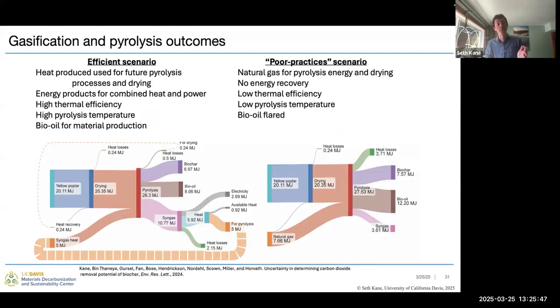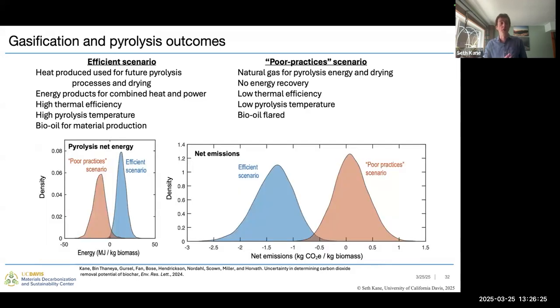In addition, it's worth thinking about that these processes can be designed in different ways. So we could have a highly efficient process where we're reusing that heat from combusting the syngas to meet our energy needs. We're using a combined heat and power process to capture the most energy we can from those products we are combusting. We have high thermal efficiency, and we're using that bio-oil for material production. Or we could have a very inefficient, poor practices scenario where we're using a fossil fuel input to meet our energy needs, or we're just flaring our energy products, and we're running this process with fairly low thermal efficiency. And those will have fairly different outcomes.